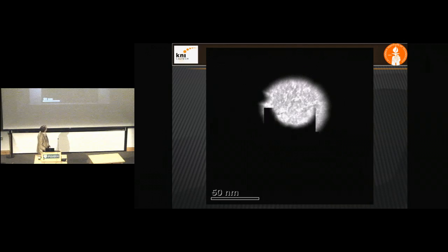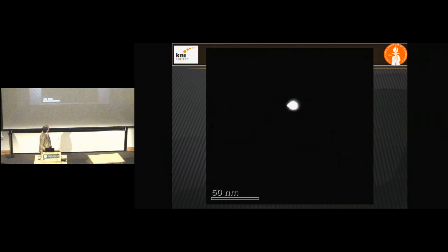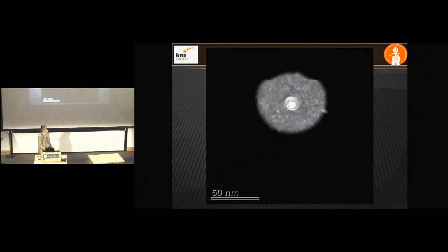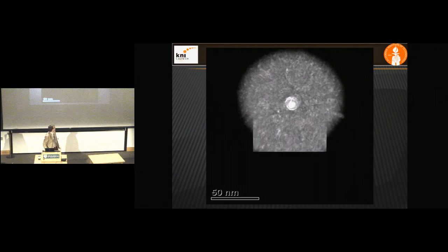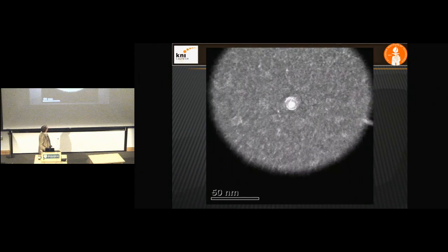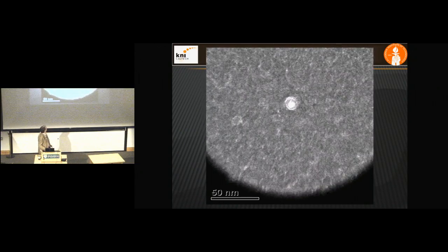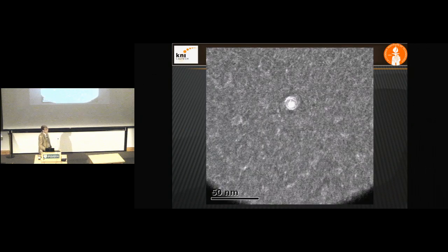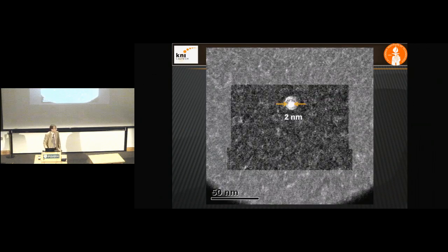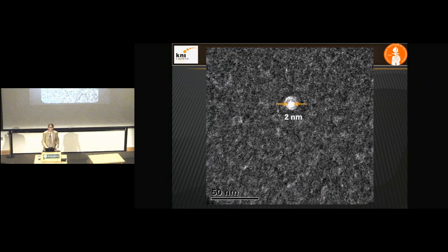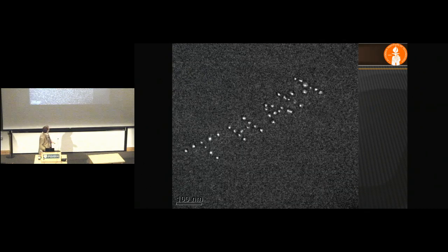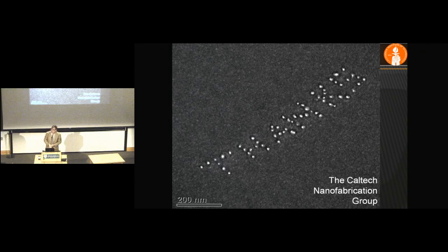You focus it down to a small spot, and then you look at it and defocus it, and you see you've actually made a small hole. Okay, and it becomes apparent if you measure this. It's actually 2 nanometers in size, and it's about 100 nanometers deep. Just done that. So I'd like to thank you for your attention.